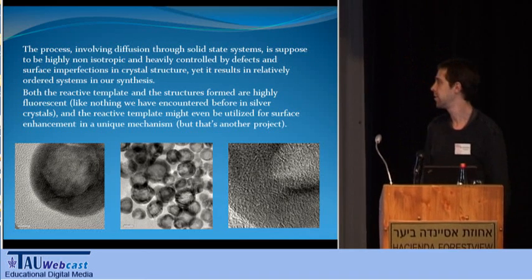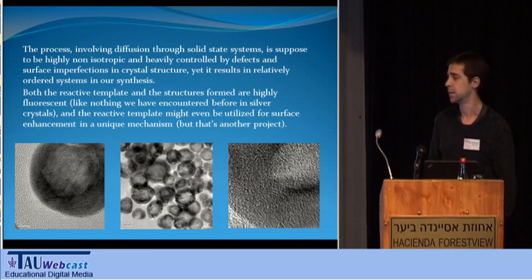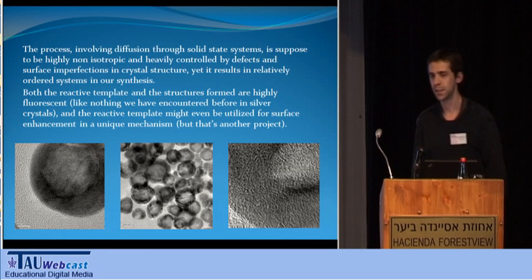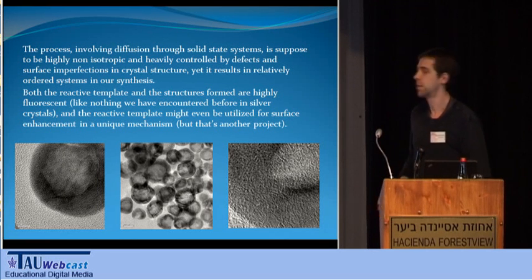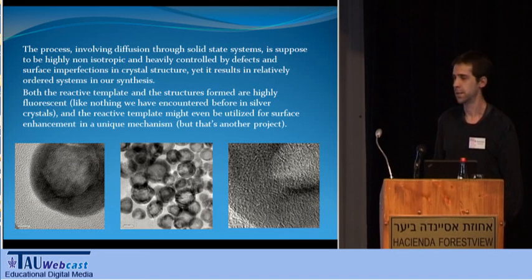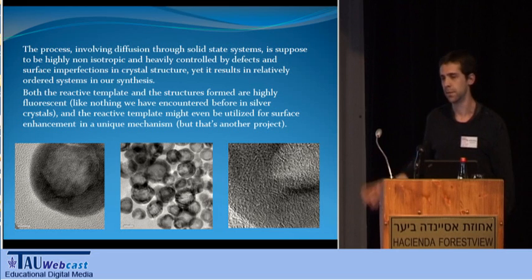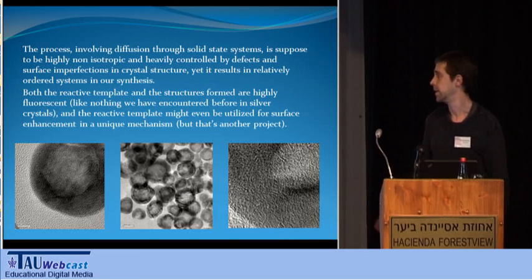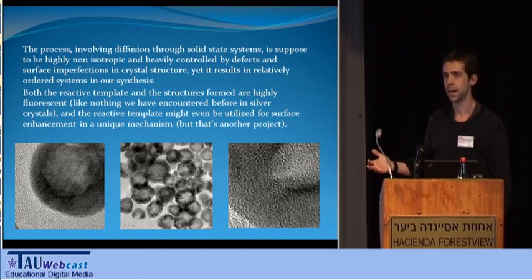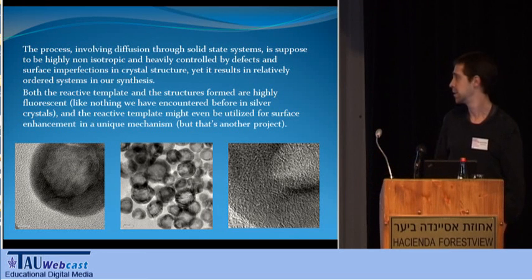These crystals are highly fluorescent, and the fluorescence is enhanced significantly after the creation of the hollow particles. I will try to convince you, if you will come to my poster, that this type of surface enhancement, I believe, is not the regular type of electromagnetic surface enhancement, and there is also a factor of what is called the chemical surface enhancement. We were also able to see some very interesting Raman features enhanced on these particles, like all types of combination bands from molecules adsorbed on these particles.